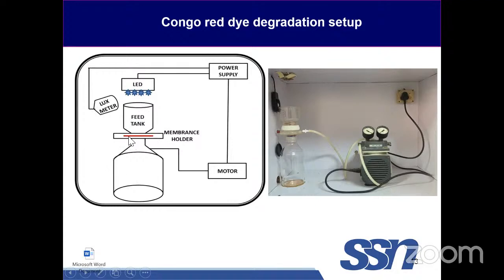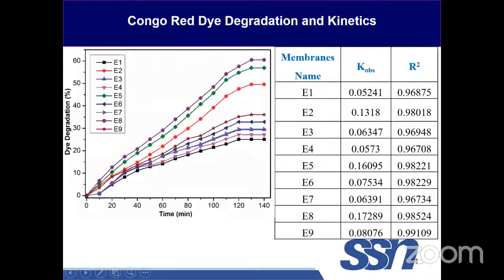The photocatalysts present in this membrane are activated by the light coming out from the LED. They react with the dye solution, and the dyes are degraded, right? This is the dye degradation efficiency of all 9 prepared membranes, in which the sample E8 gave us the highest degradation efficiency of 60%, right?